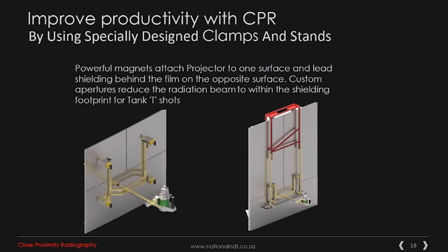The application of this technology can also be utilized in tankage, both in corrosion monitoring of existing tanks and in new fabrication builds. Powerful magnets attach the projector to one side and lead shielding sits behind the film on the opposite surface. The custom apertures again reduce the radiation beam to within the shielded footprint for tank T-shots.